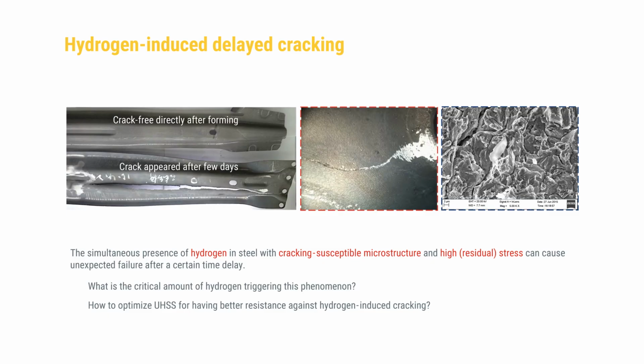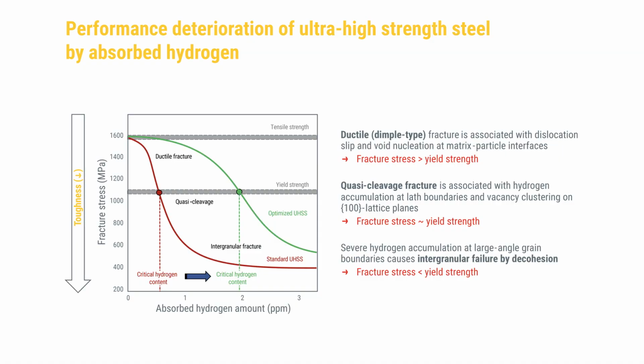This happens usually with a time delay, because hydrogen needs to go there, needs to aggregate, needs to create some micro damage that as such is not yet critical, but by further accumulation becomes critical, and that's what we call delayed cracking. That means the failure happens after some delay time and is therefore very unpredictable. This situation is disruptive to production. It is of course extremely costly, because in cases you have to throw away fully finished or mostly finished equipment that you cannot repair. And of course, when such a situation makes it into service, it's a severe risk in terms of operational safety.